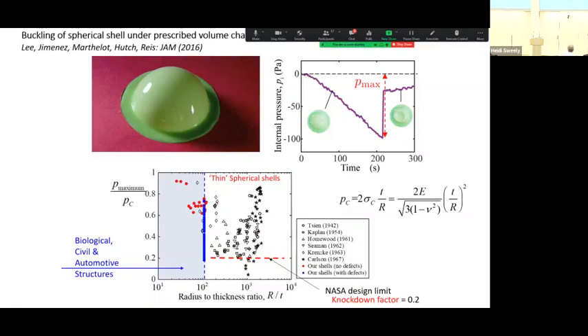There's some R over T dependence there. But the thing to take notice of here, and it's because some of these shells were manufactured so carefully, that a few of the shells, even way back, there was a group at Stanford that did electroplating of shells on very carefully machined wax subsurface. So they electroplated these shells, polished them, and then melted out the wax. They could make very accurate shells. And you can see some of them buckled up close to the classical value, but still enormous scatter. And as I say, still today, for unstiffened spherical shells or hemispherical shells, we still use that factor of 0.2, knockdown factor.